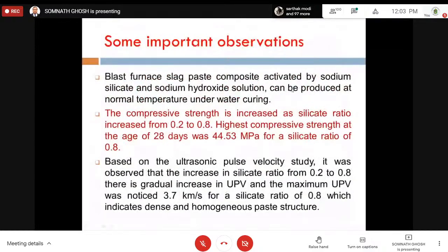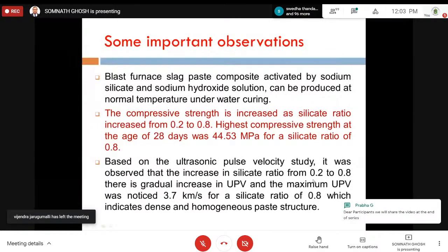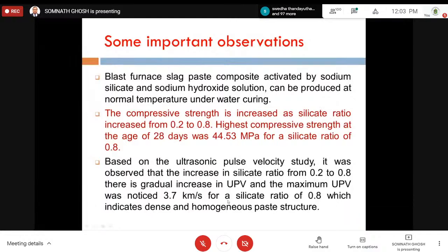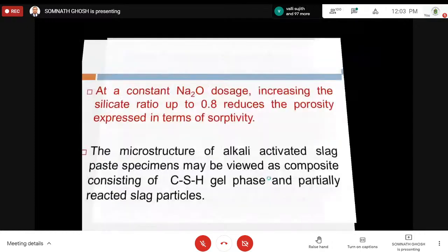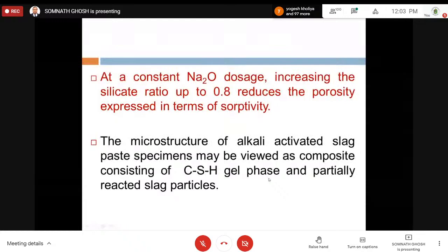Now you see, the compressive strength is increased as the silicate ratio is increased from 0.2 to 0.8. Right? So it is up to this, at 0.8. Pulse velocity, of course, 3.7 is around we have seen, right? It is also, we have seen, increased with the increase in silicate ratio. So silicate ratio has got an effect on pulse velocity also.